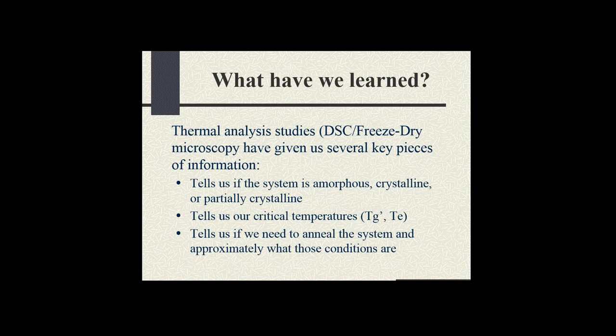So what have we learned from the thermal characterization? It tells us a couple of things. Is the system crystalline, amorphous, or is it a mixture of the two? Tells us the critical temperatures, or at least tells us the glass transition or the eutectic melting temperature. And then the microscopy, the freeze-dry microscopy, tells us where that collapsing event occurs.